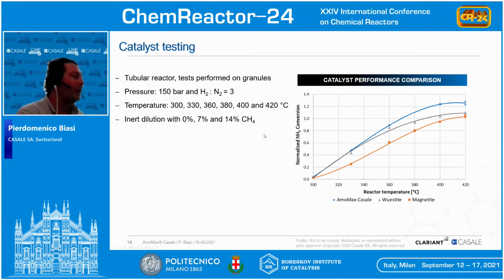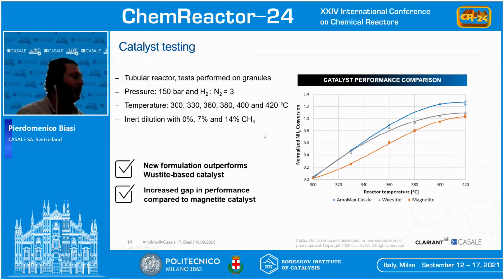And what we observed is that we found a formulation that was outperforming the classical wüstite and magnetite formulation. It was performing really well at high temperatures, especially when we are limited by kinetics and thermodynamics. So the new formulation was outperforming, and also increased the gap to the classical magnetite catalyst.